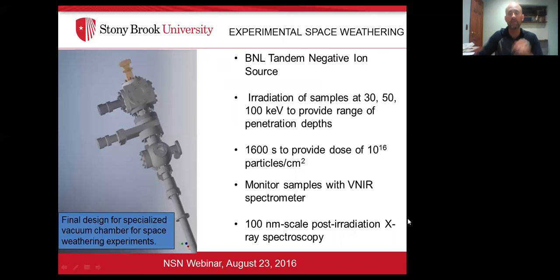And so one of our goals is to simulate this process in the lab so we can learn more about it. We're using the tandem negative ion source at Brookhaven National Laboratory. We're irradiating samples at 30, 50, and 100 kiloelectron volts with hydrogen atoms to provide a range of penetration depths into the sample. We use specific doses, and we monitor the samples using visible near-infrared spectroscopy and 100 nanometer scale X-ray absorption spectroscopy, which is going to tell us a lot about the chemistry and structure of the materials